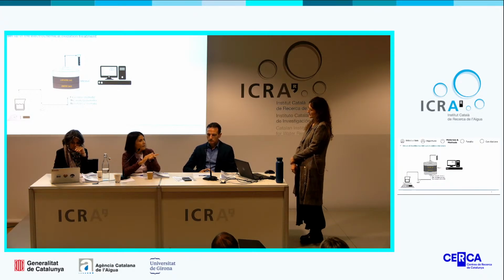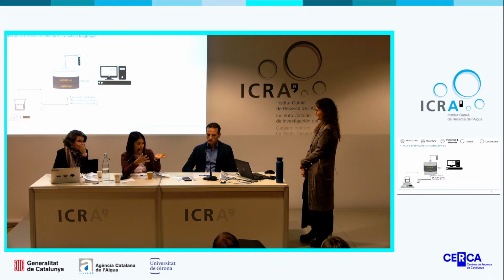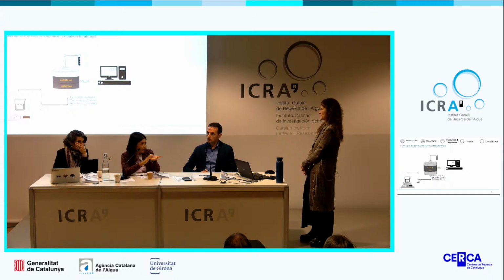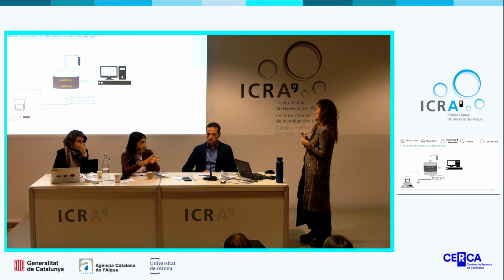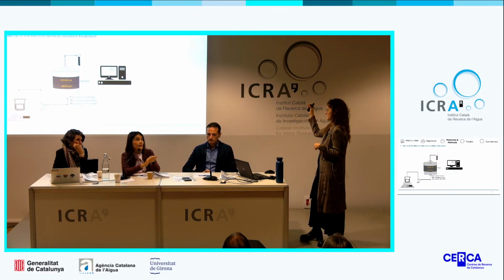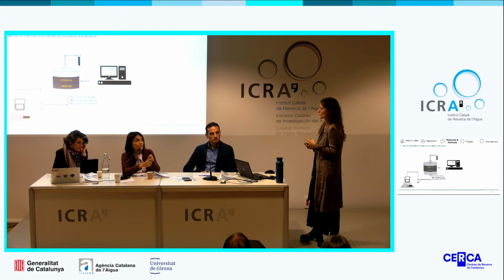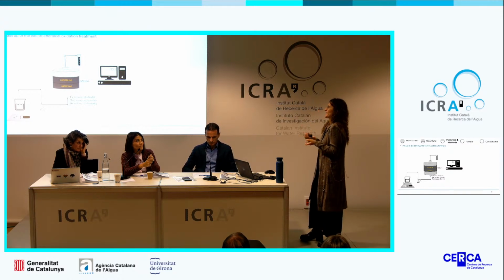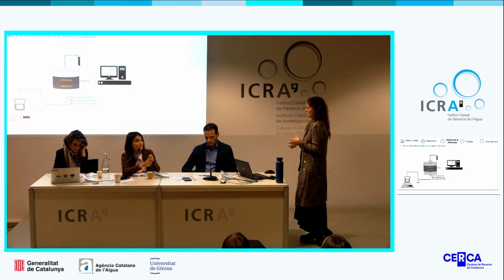You have your electrode materials, then you pass your solution, and you have the absorption of sulfamethoxazole and the other antibiotics. Then to check this absorption capacity, you run an experiment without current, right? And then you extract the amount of antibiotics absorbed. Well, we just did it to quantify more or less. The samples are quantified in the Q-trap, and the extraction with methanol was just performed once to confirm the degradation of the antibiotic.